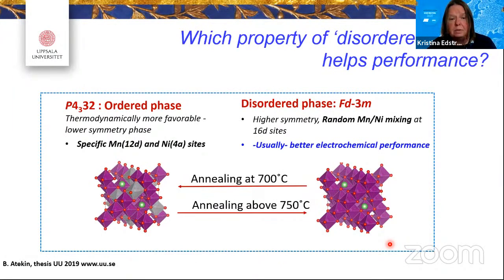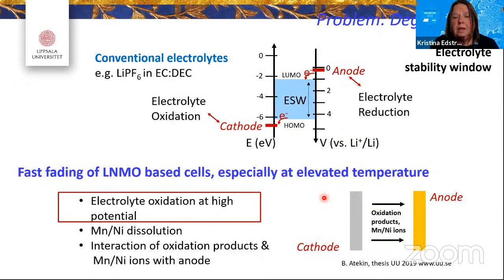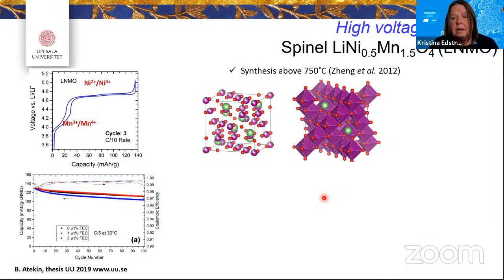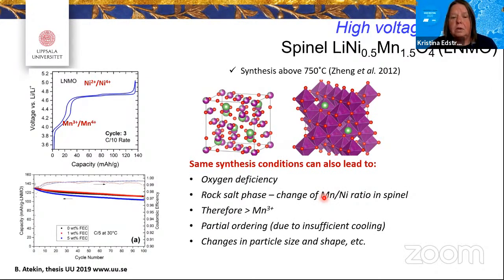And what structure should we have? If you make this material, it has an ordered phase and a disordered phase. And just to make the story quick, the disordered phase is usually the better one. Looking at the disordered phase and at the synthesis of this, we can say that using the neutrons we find some oxygen deficiency. We can find there are changes in the material forming, instead of the spinel going to a rock salt phase structure. There is more manganese than nickel. We have a partial ordering. There are changes in particle size and shape. So this work to really penetrate the synthesis conditions to come to the right structure that you can really use is what is happening at a number of companies at the moment.